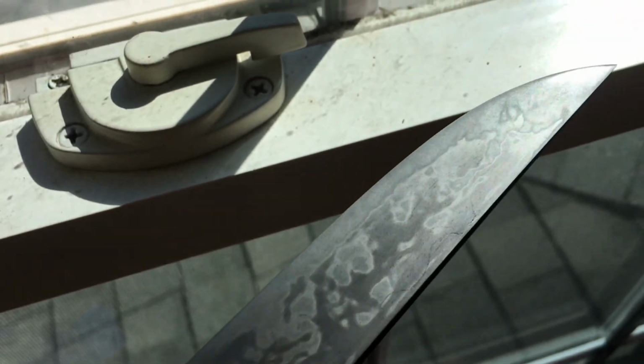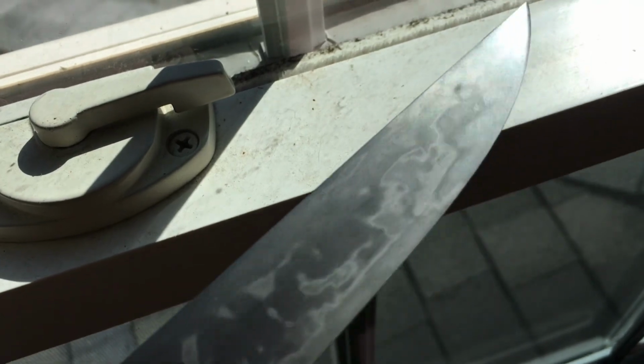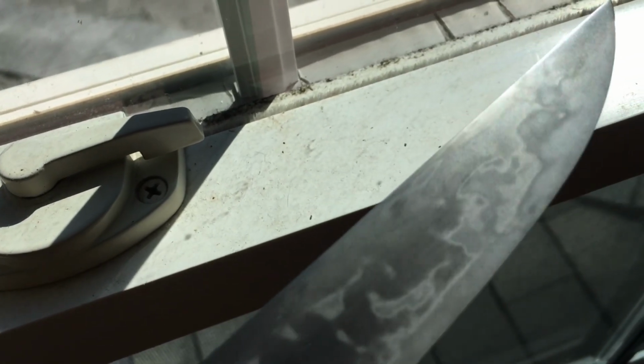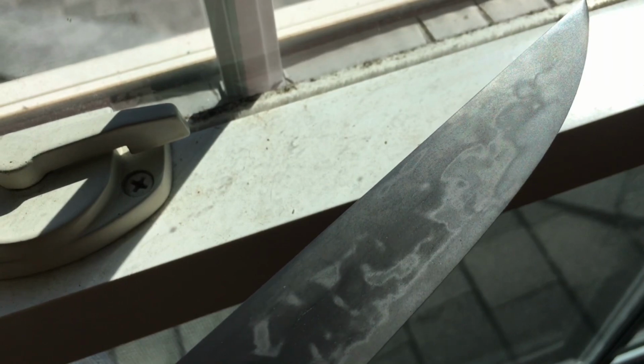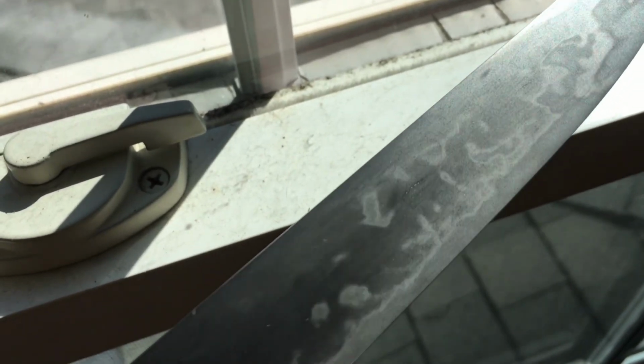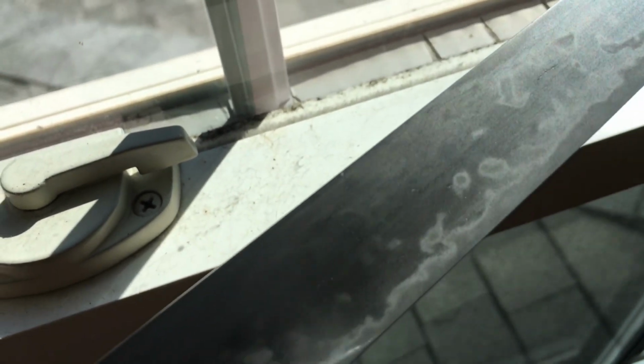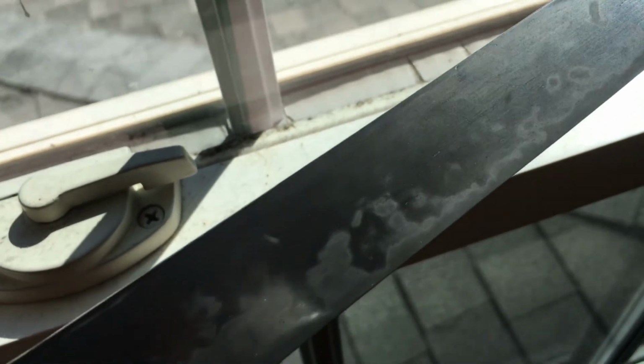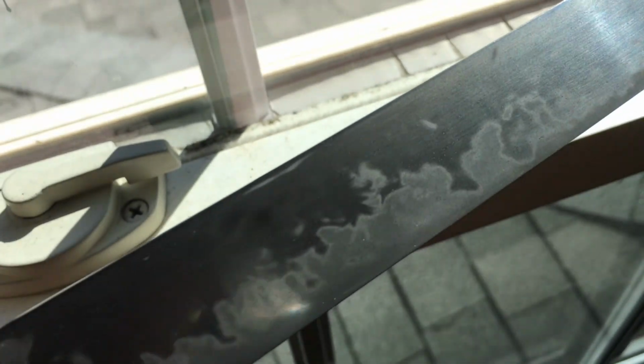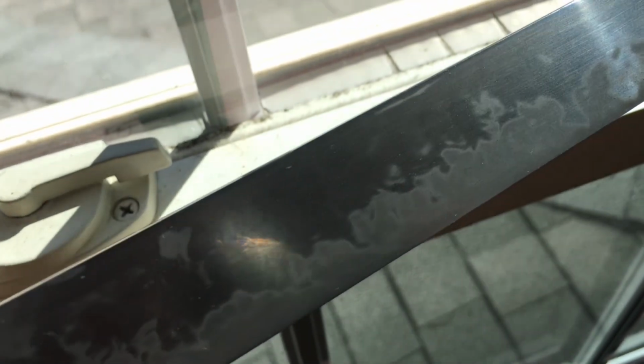All of this activity, the muneyake, the tobiyaki, everything is as a result of heating carefully in the fire and quenching in water. None of this has anything to do with clay. I don't use clay for almost any of my work. All of this is due to the heat zone that's in the blade, the amount of time I'm leaving it in the heat, the way that I'm moving it or not moving it in the water, and the angle at which it's put in the water. So all of these factors completely change what's going to happen when I harden this blade.